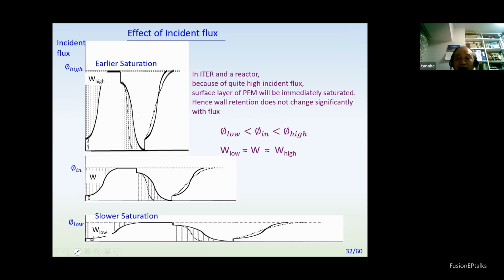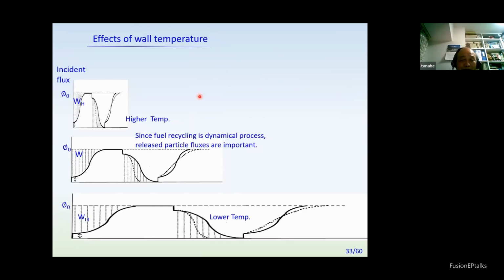In the ITER reactor, with quite high incident flux, the surface layer of the plasma-facing material will be immediately saturated. Wall retention does not change significantly with the flux—it's nearly the same. But if you go to high temperature, the retention becomes very low.